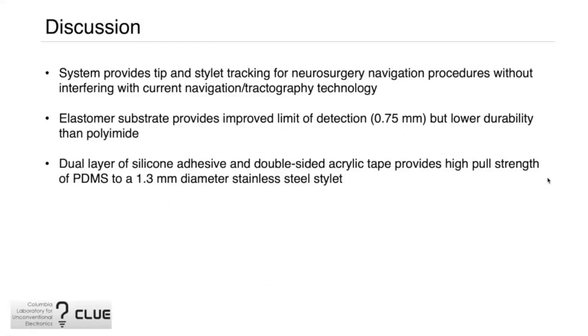Lastly, we found that a 2-layer adhesive stack of silicone adhesive and double-sided acrylic tape provides for a high pull strength of the strain gauges on PDMS to the 1.3 millimeter diameter stainless steel stylet. We think that this device is the beginning of using mechanical sensors to track small amounts of movement on thin objects, for example, 1.3 millimeter diameter rods, without the need to fully redesign tracking tools.